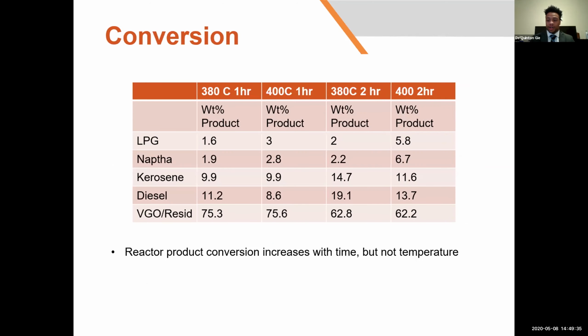So here's a table of our conversion, just to give you a rundown on what our reactor is actually producing. As you can see, as temperature increases, we start to create less diesel when using the kinetics that we modeled from our literature. That led us to use lower temperatures, because if we start to create less of our high commodity products, our NPV starts to go down.